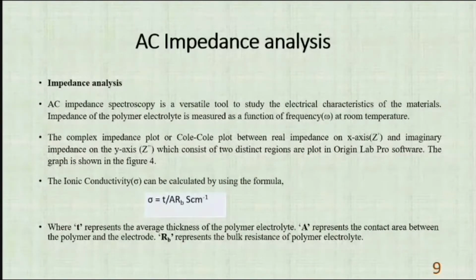The ionic conductivity is measured by the formula sigma equals thickness over RB times A, where the average thickness of the polymer thin film membrane is taken. A represents the contact area between the polymer and the electrode. RB represents the bulk resistance of the polymer electrolyte.